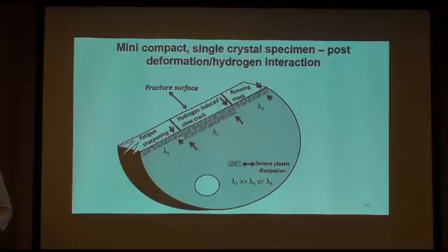People feel that cleavage probably doesn't have anything to do with plasticity. We claim that all what we get in the cleavage plane is controlled by the plasticity. This is the major concept here. And we could measure it, and we could calibrate it, and by this I don't want to bother you more.